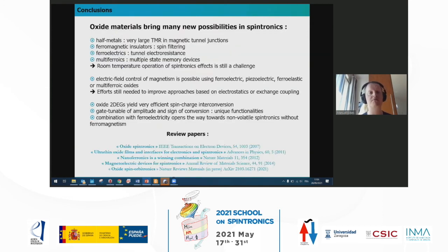So I'm coming to my conclusion. I hope I've shown you that oxides bring many new possibilities in spintronics. You have a bunch of materials to choose from. Half metals can give very large TMR. Ferromagnetic insulators also give large TMR due to spin filtering. Ferroelectrics as barriers give you large tunnel electroresistance. You can make neuromorphic devices out of them. Multiferroics can allow you to have these multiple state devices, and you can also use multiferroics to control magnetism by electric fields, although efforts are still needed to make things really robust and reproducible over many cycles at room temperature. And in the final part, I showed you oxide 2DEGs, which are very good materials for spin charge interconversion.